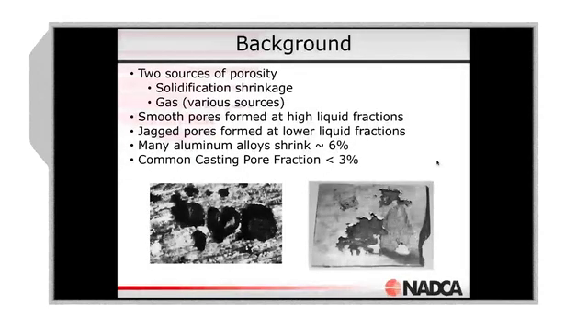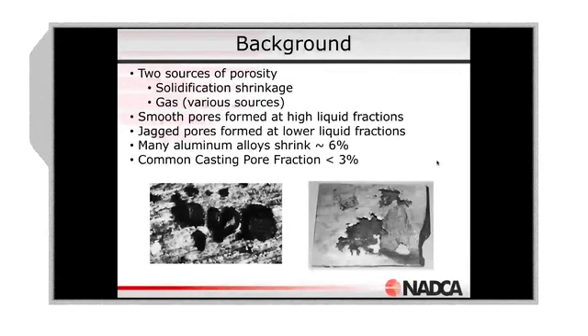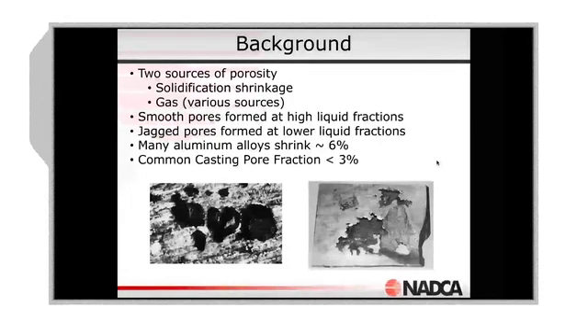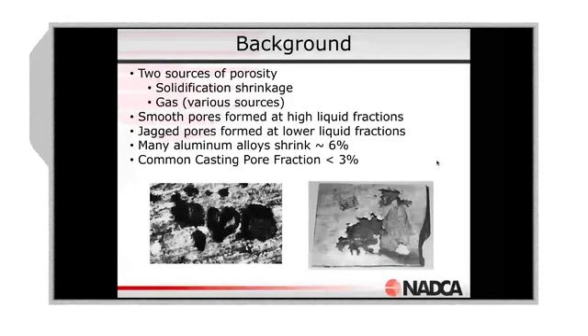When we look in the literature about the level of porosity in die castings, we pretty much never see a casting with more than 3% porosity, and certainly often less than that. So what this implies is that we can't discount one source of porosity over the other. We're going to get air entrapment or gas entrapment, and we're going to get shrinkage porosity. Therefore, when addressing porosity, we have to think about both — we can't just focus on air entrapment or just on shrinkage porosity.